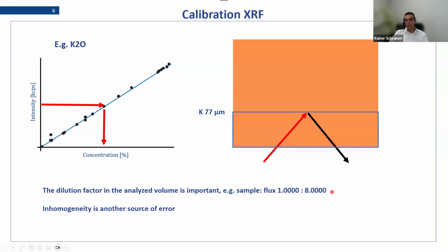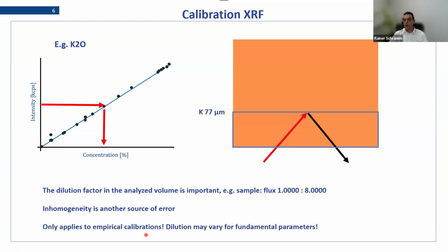But the other really important point is the error we see in the real world is the inhomogeneity here in that volume. And you will see that this is much bigger than any kind of weighing errors. And so the most important message here is you have to keep the dilution constant and not the absolute mass. But of course, this is only important when you do empirical calibrations. That means that you don't do any kind of theoretical correction in XRF, so that you calibrate your X-ray with standard materials, and you prepare them exactly in the same way as your unknown samples. You keep everything constant, also the mass and the dilutions.